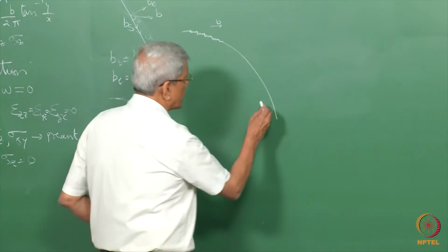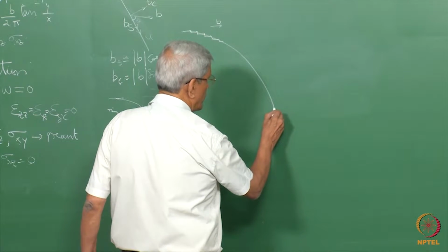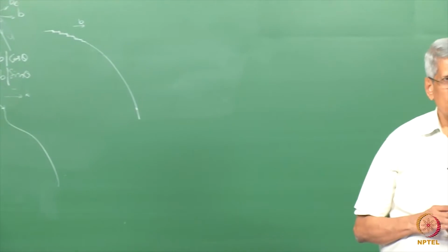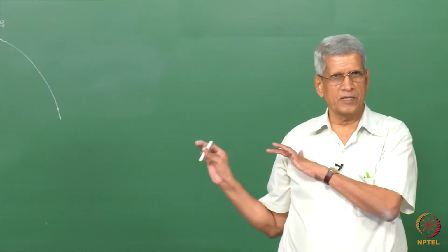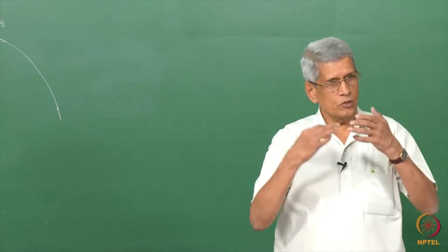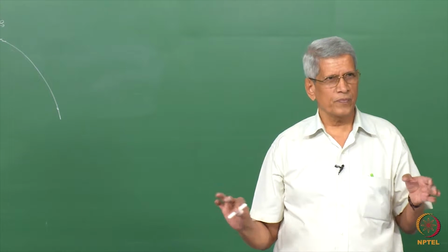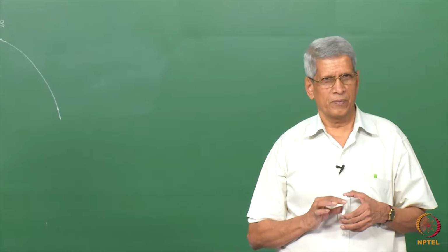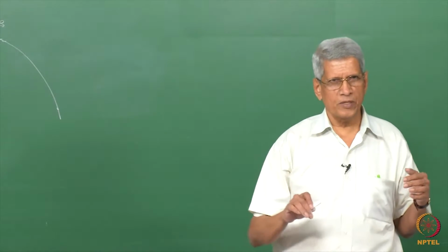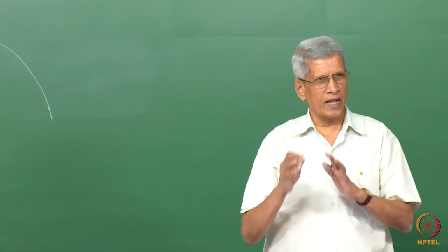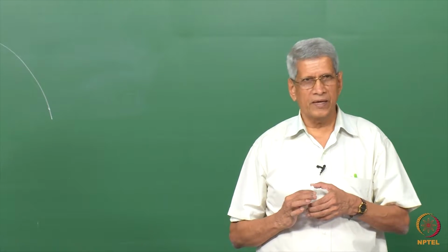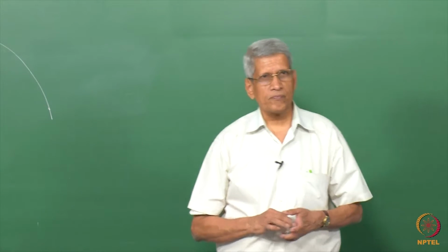Depending upon that, here if we come in, the edge component will become more, the screw component will become less, that length will vary. This way also we can look at it. Both the options are available for computationally determining the stress field and strain field around a mixed dislocation. To do that we have to split them into screw component and edge component. Either we take the line direction to be the same and take the Burgers component, or keep the Burgers vector the same, and the line itself can be taken to be an edge and a screw. Both options are available.